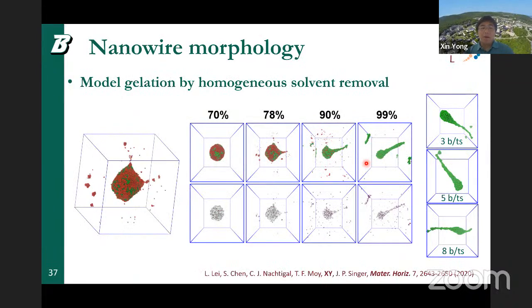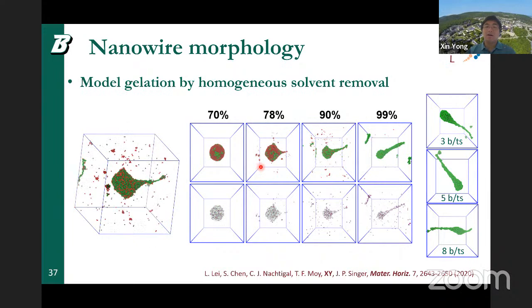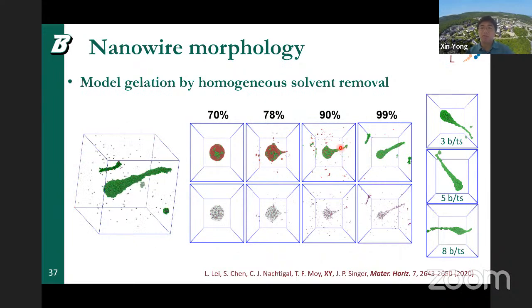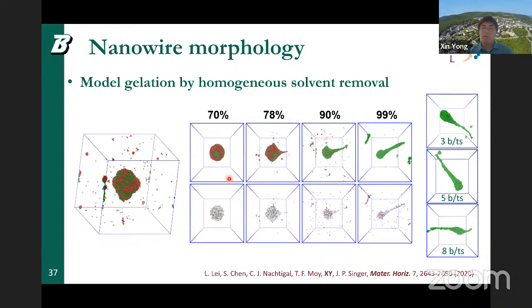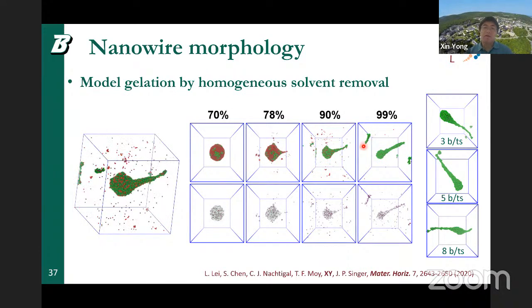Now we want to test our hypothesis. What if the viscosity transition is homogeneous? So here we model this gelation. So we believe that the gelation will help that. We model the gelation by, instead of evaporating the solvent, we just homogeneously remove it throughout the entire droplet. So in this case, the polymer concentration will be homogeneous throughout the whole droplet. And now we see the characteristic deformation is very different, where the pseudopole still forms, but then the deformation will now involve the entire droplet and elongate it. So we get a